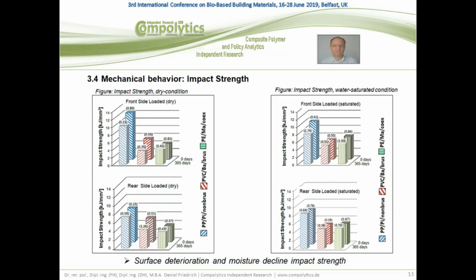In terms of mechanical behavior, we observed that we always received a lower impact strength for all three sample types, but the highest losses were measured for the first type with the polypropylene matrix, and the least decline we measured at the front side, the loaded front side, which was also exposed to the natural weathering for the third type with the co-extruded top layer, but as can be seen, we overall receive declines in impact strength, which is an important factor for facade application, which is exposed to also mechanical impacts.